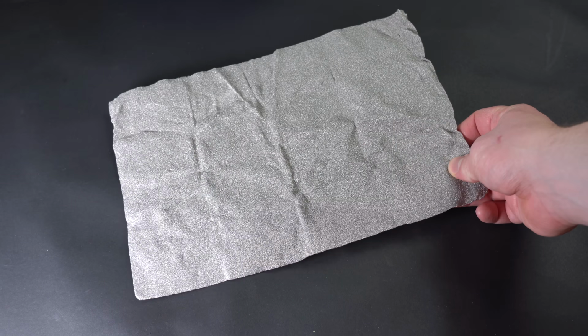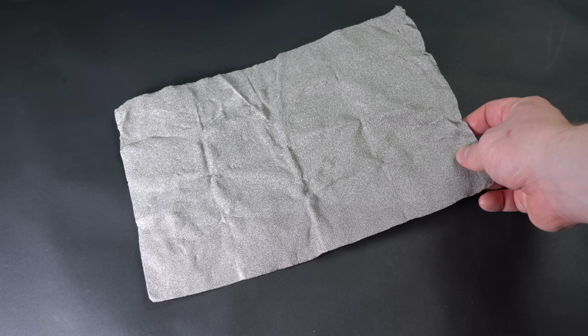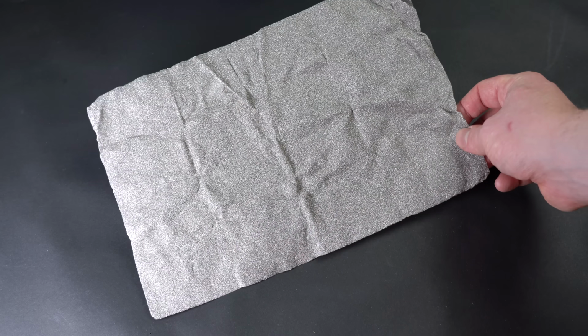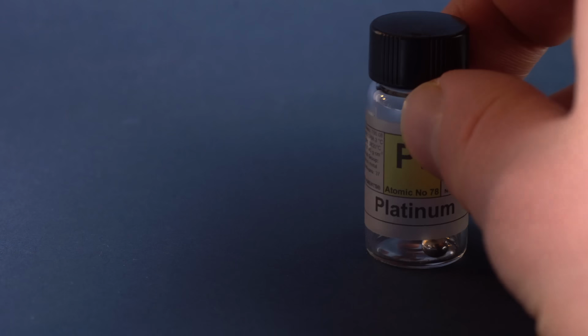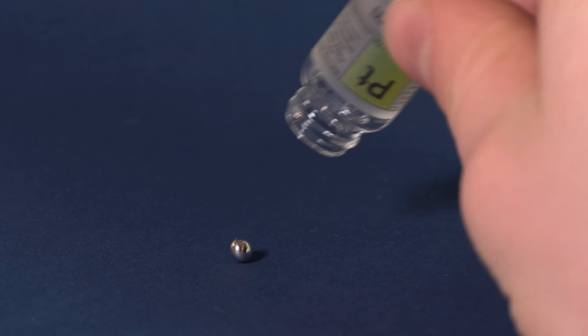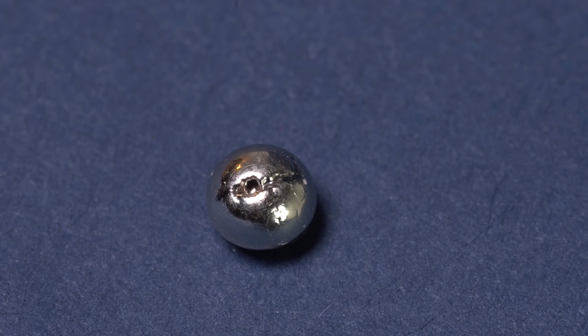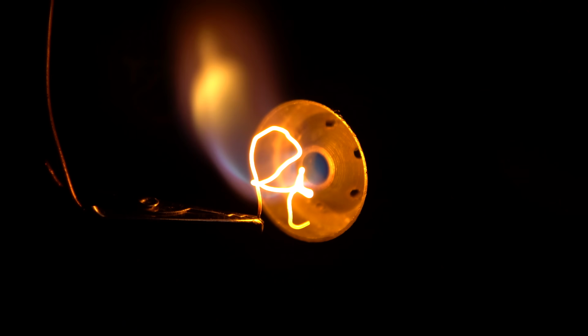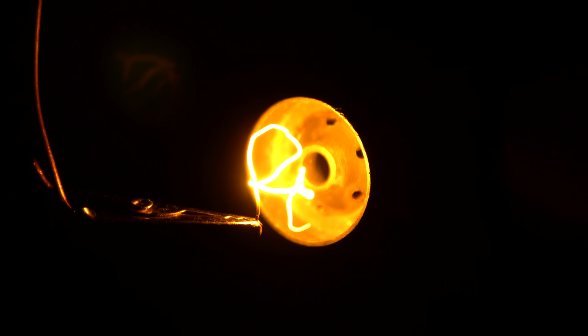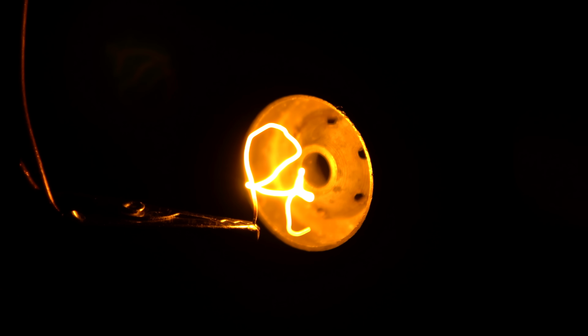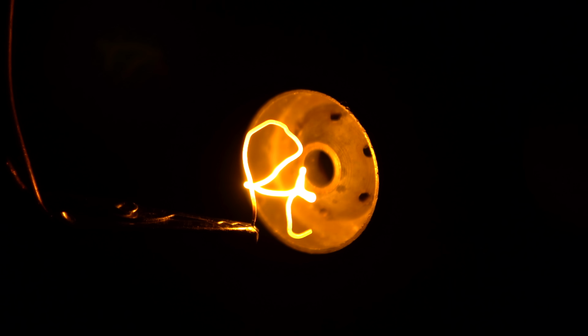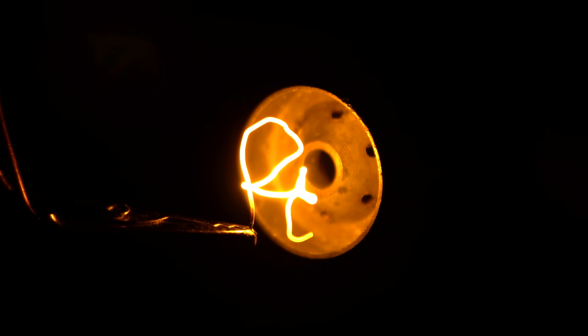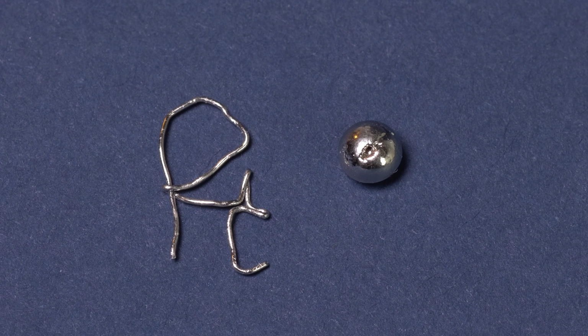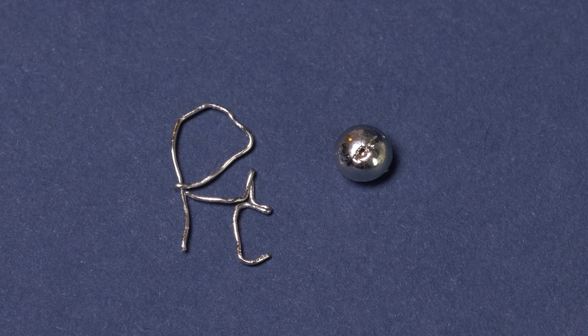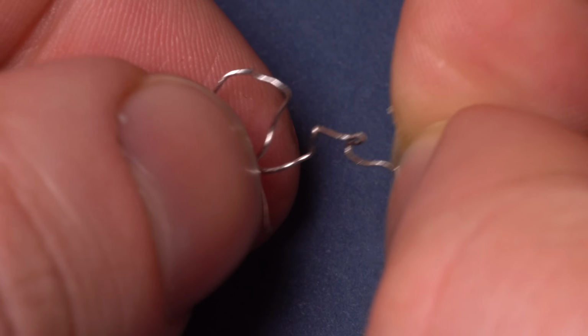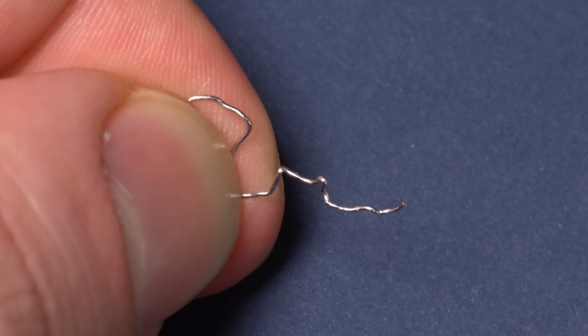To do that, first we need to make a platinum electrode we'll use for oxidizing hydrogen and generating electricity. If you didn't know, metallic platinum is a great catalyst, which means it increases the rate of chemical reactions. For instance, if we pass a stream of propane through a heated platinum wire, it will start oxidizing on the surface of the wire and at a significantly lower temperature than it will burn under normal conditions. Since pure platinum is too expensive to make electrodes from, a thin platinum film on the surface of another metal will suffice for my experiment.